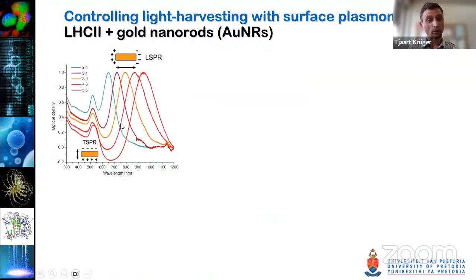What makes these systems very interesting is that the spectroscopic properties are highly tunable. Especially if you tune the aspect ratio by changing the longitudinal component, then one can strongly tune the absorption and the fluorescence properties of the system.